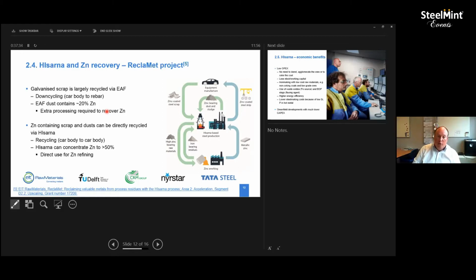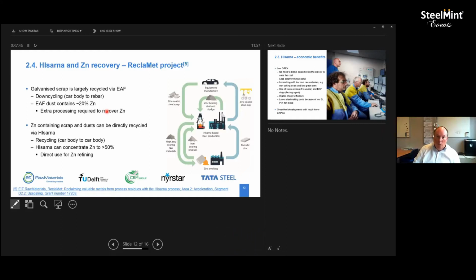And EAF dust can contain up to 35%, but a lot of places it's around 20% zinc, which is then upgraded via intermediate processes, including the Waelz kiln, to be used as a raw material for zinc production. If it's much lower than the 20% zinc, which also happens, it's often just landfilled, and that zinc is lost.